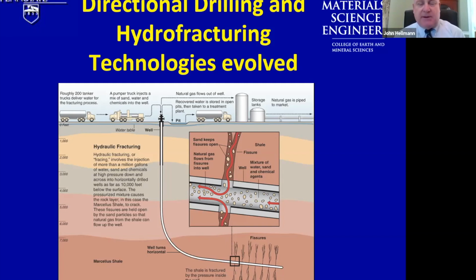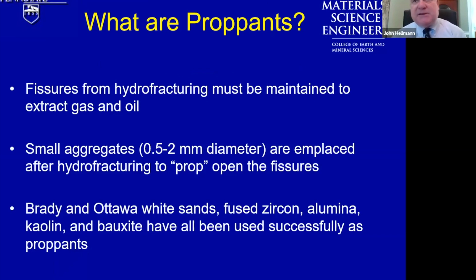Those fractures in the surrounding shale are what release the natural gas from the shale to the wellbore. But the intent is to increase the size and length of those fractures in the rock to be able to achieve more surface area and retrieve more gas. Hence, hydrofracturing is employed, where millions of gallons of water laced with ceramic particles known as proppants are injected into the wellbore. The wellbore is then pressurized, and these cracks that were created by the shaped charges expand, grow, and are held open by the ceramic particles in the hydrofracturing mix, the proppants. So the intent is that for a proppant to perform well, they need to be sized in the range of about 0.5 millimeter to 2 millimeters in diameter.